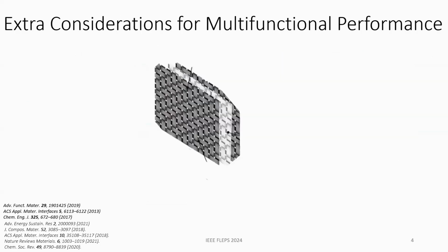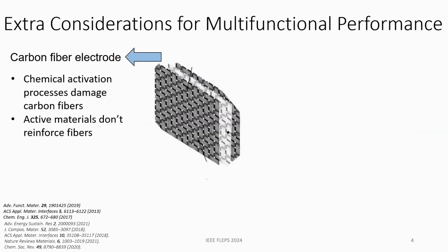There are a few extra considerations when it comes to structural supercapacitors, because it's easy to end up reducing both the power and energy density instead. When it comes to the electrodes, already for monofunctional supercapacitors, there's a concern with active material delamination and degradation over time. And then we need to put it on a substrate that is stronger, such as carbon fiber. Any chemical activation processes for the active material can end up damaging these fibers. And the active material itself won't contribute to reinforcing, so it can fall apart very easily.